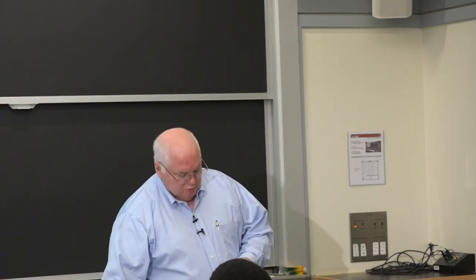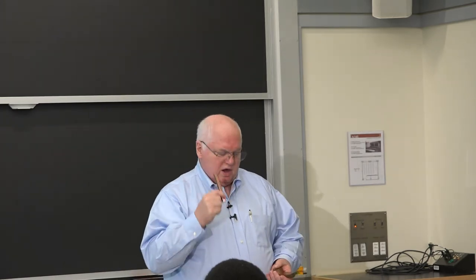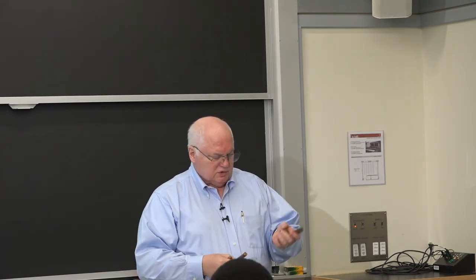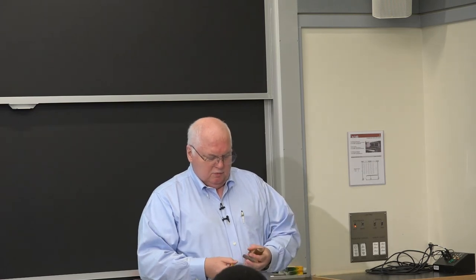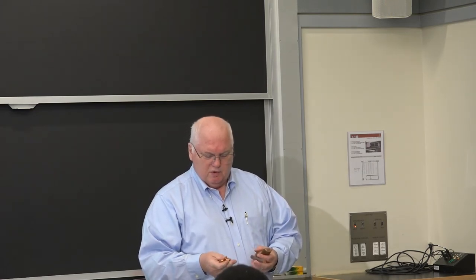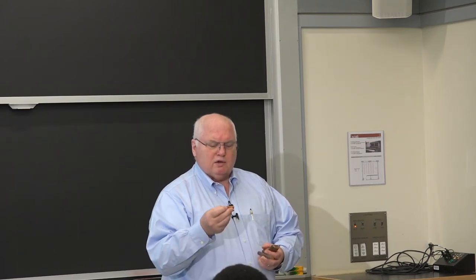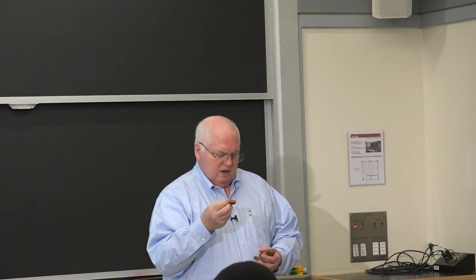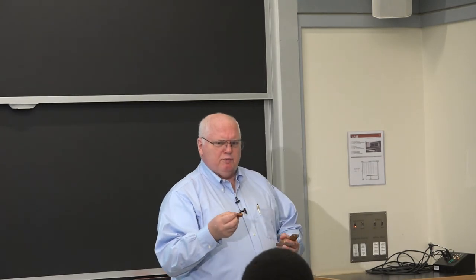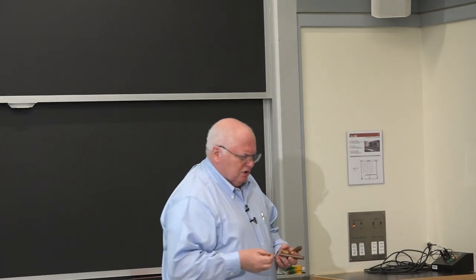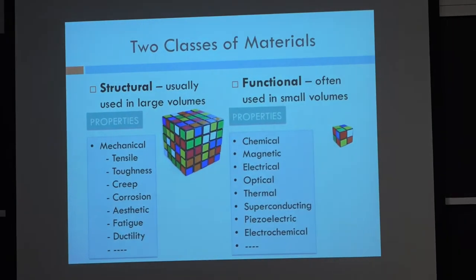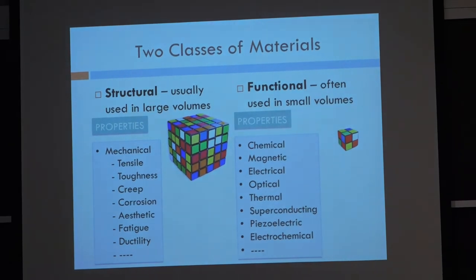It turns out what we ended up using, and in fact, this is ultra-fine grain as opposed to this coarse grain. This was the casting that they wanted to use, but someone else came up, a big copper company, with an ultra-fine grain product which has tremendous ductility and strength, and in fact, that was the big fight. It had too much elongation, okay? How can you have too much elongation for a structural material? So this is actually a tensile specimen, and you can see the ductility of the copper. So those are some examples of things that you can look at of different structural materials.